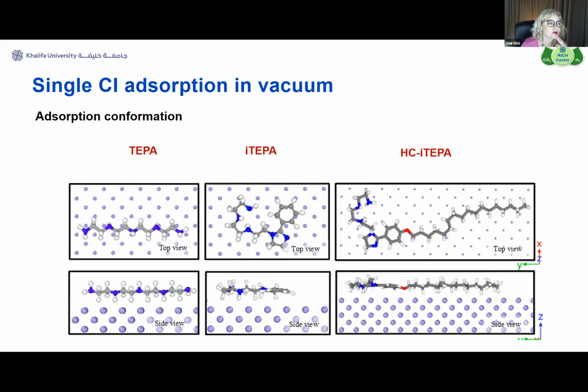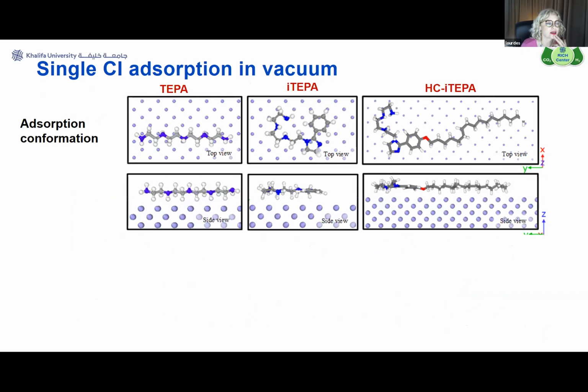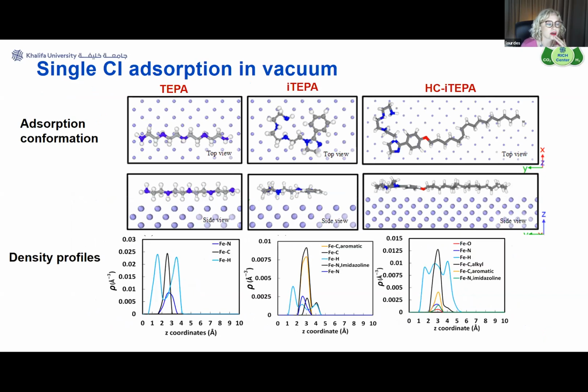So first, I'm going to show you the adsorption conformations in vacuum. Of course, this is what is expected. The molecules will adsorb on the surface because you have nothing more. There are no more interactions. We have calculated the density profiles to identify which groups of the three molecules.